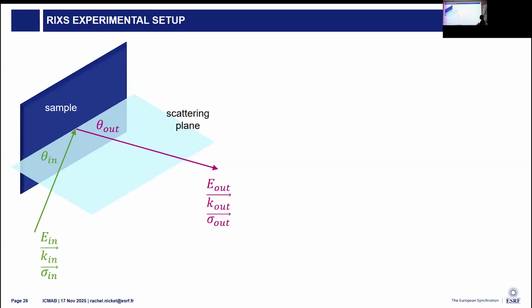We then choose, based off of how we position the spectrometer in the horizontal direction, which point in momentum space we want to look at. So we align the sample with the incoming beam, and then we align the spectrometer such that we can probe a particular point in Q space. So this would be standard scattering geometry. And then we have the option to measure the polarization of the outgoing beam.